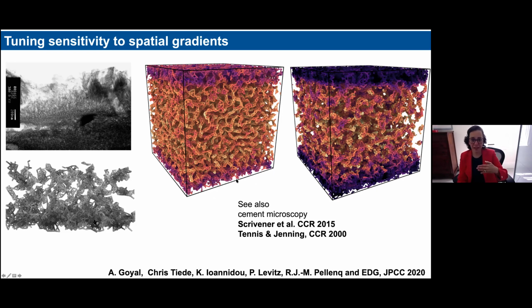And so you can see that, by doing this, we also find out that the early stages type of interaction that leads to these fibrils, this more anisotropic growth of the gel, and this earlier percolation, actually favor a type of structure that is less sensitive to these spatial gradients, whereas the later stages of the interactions are much more sensitive to the spatial gradients, and so the heterogeneity of the gel formed in this case, that we had already seen in the other simulation, becomes even more enhanced.